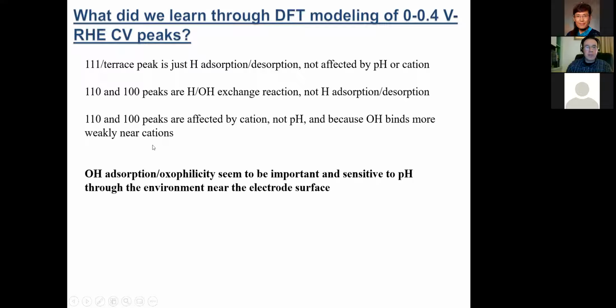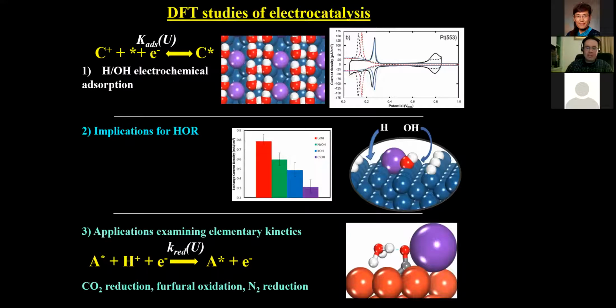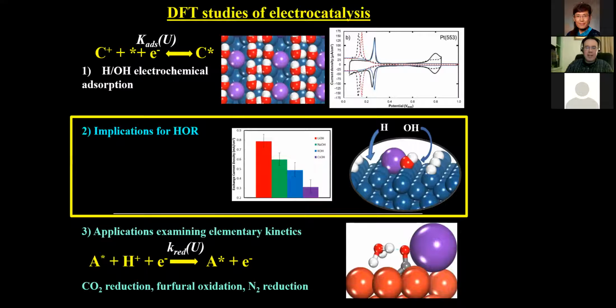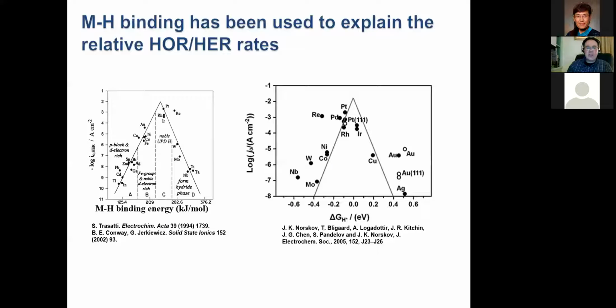So hopefully I built up some credibility that DFT can be used in an electrochemical environment to understand how processes are going on. But now I want to extend that to say, well, what does that tell us about catalysis? The hydrogen oxidation reaction, I showed you this figure earlier, is thought to be predicted by how strongly hydrogen binds to the surface. And I just showed you results, in a very specific system, that said hydrogen doesn't adsorb with a dipole. It interacts strongly with the metal. It doesn't interact with solvent. It's not affected by the change from sodium or the change of pH and change of cation.